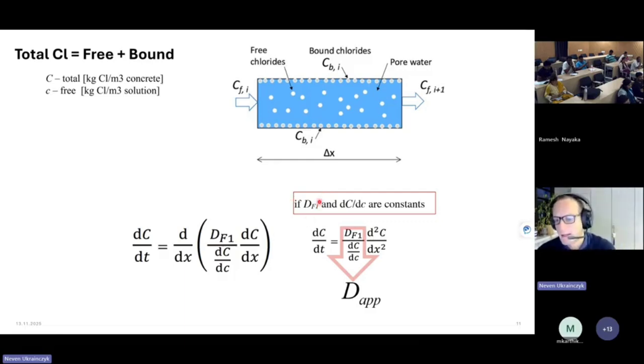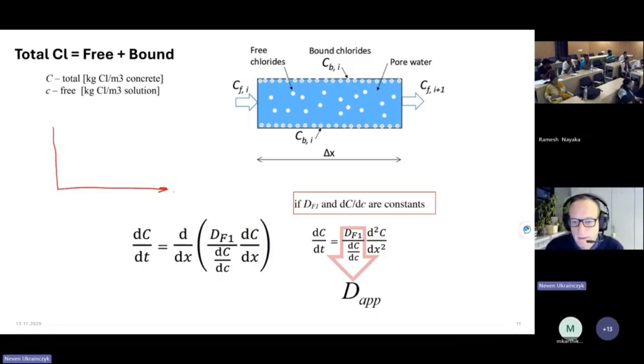But then only if the effective diffusion coefficient, which is basically the first Fick's law diffusion coefficient. First Fick's law gives you the flux. The flux is proportional to the diffusion coefficient and the concentration gradient. And if this effective diffusion coefficient is constant, and if the binding isotherm is linear, so that the change of the concentration is a function of the free concentration. This would be the binding isotherm. So if you have the free concentration and you have the total here, or bound, it doesn't matter. Then if this is linear, then this slope is constant.